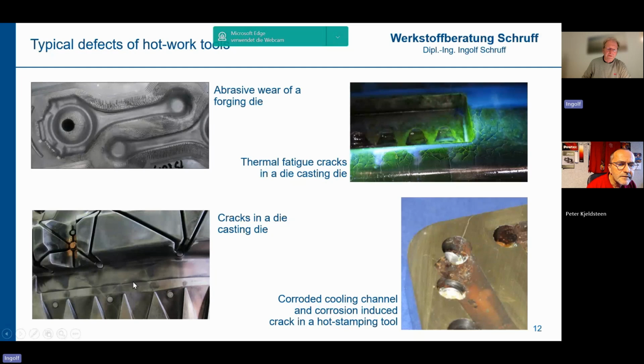In the die casting die, we see massive cracks here. Wow. Yeah. I hope it is visible. And then up here, this is a typical appearance of the so-called thermal fatigue cracks or thermal shock cracks. Here we made them visible in the magnetic particle test with ultraviolet light. So each green line shows a fine crack. And usually these cracks appear in a kind of a network as we see it here.